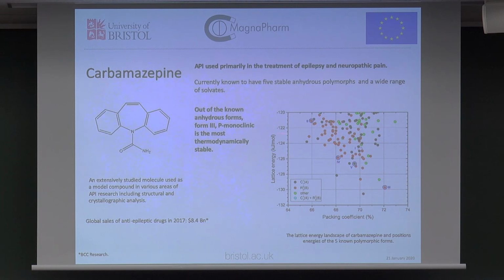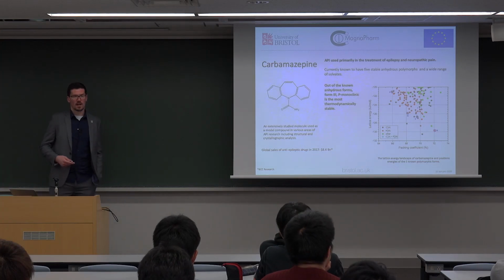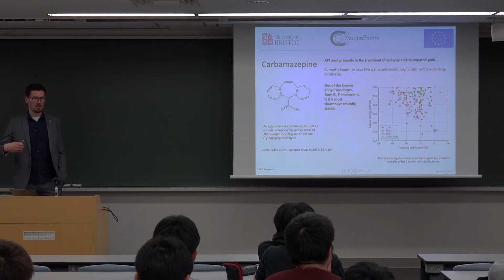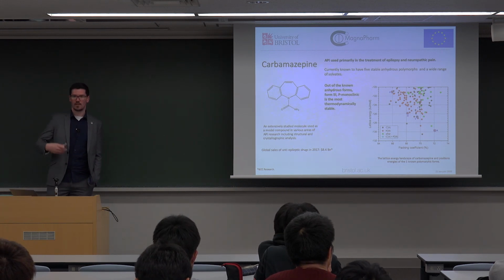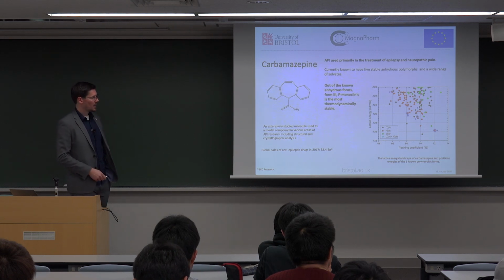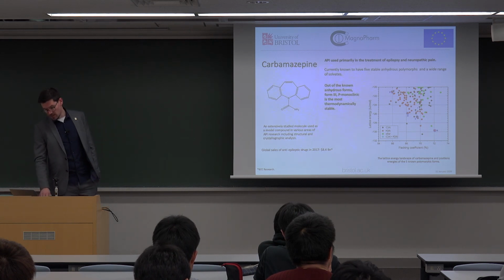And this is the CSP here, crystal structure prediction. So each one of these points is a new energy minimum for this crystal to exist. And the known forms are circled with blue circles. Form 3 is that red one at the bottom. That's the one we see if we just dissolve it in ethanol and let the ethanol evaporate. And the other forms are found by heating it up, cooling it down, additives, different solvents, that kind of thing. But it's a very well studied drug.